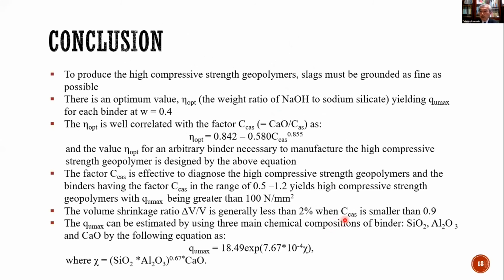Now, conclusions. To produce the high compressive strength geopolymer, slags must be ground as fine as possible. And there is an optimum value, ηopt, the weight ratio of NaOH to sodium silicate, yielding Qmax for each binder at Ws equal 0.4. The ηopt is well correlated with the factor Ccas as this equation.